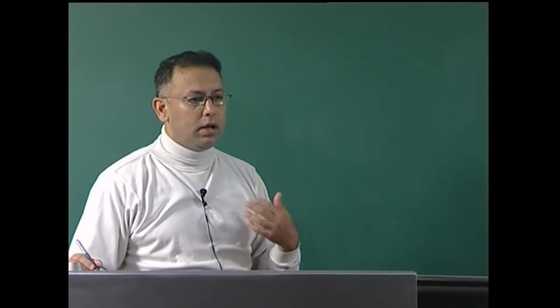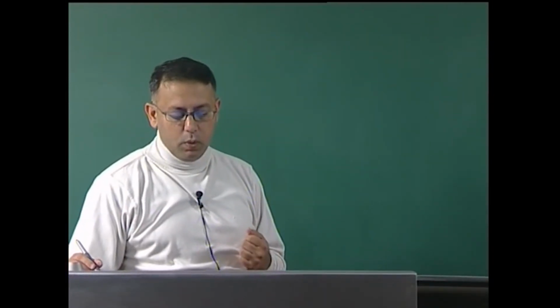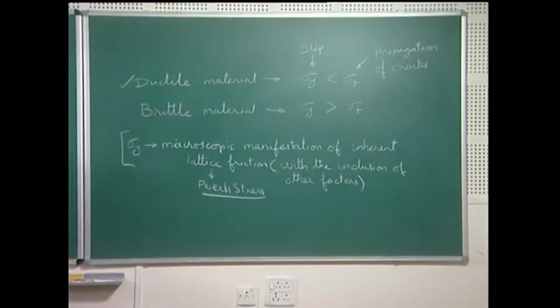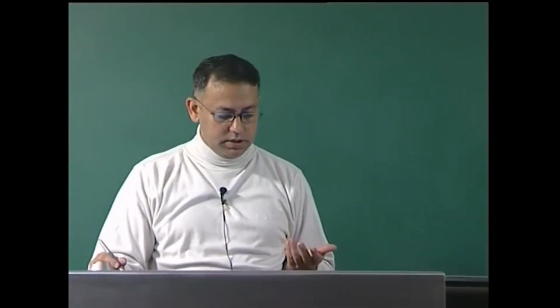A covalent material typically has a high Peierls stress and therefore has a high yield strength, and therefore, if I am trying to plastically deform a covalent material like diamond, it turns out it is difficult, and typically an ionic material, which again has the scenario of a high Peierls stress, would fail by brittle fracture rather than plastically deforming. Therefore, if I am looking at any property, then the bonding characteristics become very important in determining the properties.